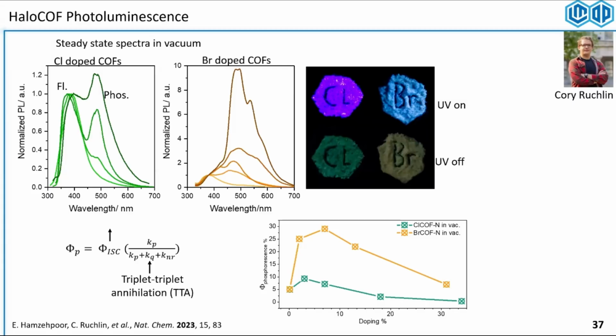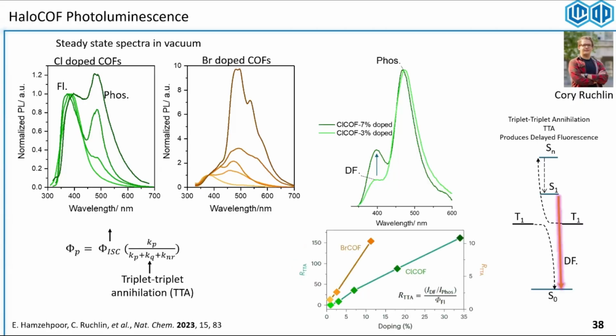Maybe we should have an optimal doping concentration where we generate a lot of triplets, but not so much that they start to annihilate each other. And we were lucky to see something called delayed fluorescence, which is an indirect way to talk about triplet annihilation.